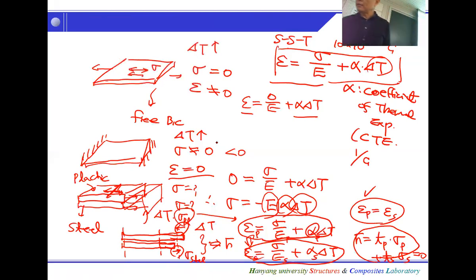Like now delta T, in that case, delta T will be negative, shrink down, because it is stress-free at the high curing temperature, no stress, nothing. Then cool down to room temperature, there will be inherent thermal stresses that would cause the residual deformation. That's why in composite material manufacturing, whenever we mold, lay up and cool down, there are always distortions, a big problem.